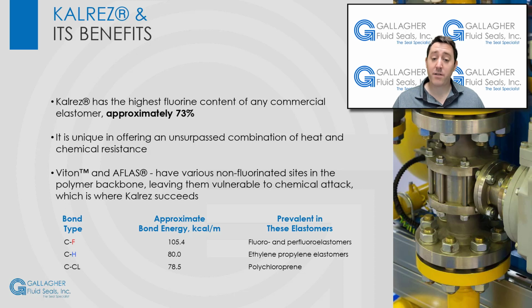Fluoroelastomers, Viton and Aflas, have various non-fluorinated sites in the polymer backbone, leaving them vulnerable to chemical attack. It is at these carbon-hydrogen sites unprotected by the polar umbrella of fluorine that the destruction of the chain can be initiated by aggressive environments or high temperatures. Furthermore, the cross-linking systems used with fluoroelastomers are phenol or peroxide, making them susceptible to attack and unable to survive temperatures over 400 degrees Fahrenheit.